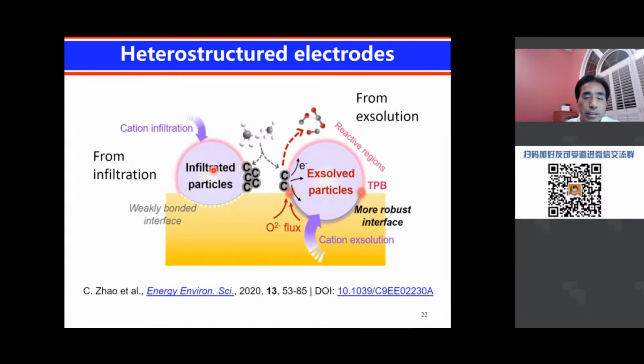Yeah? So here, just to schematically illustrate, you can introduce a catalyst by infiltration, and that will interact with the parent oxide and then create heterojunctions. Or by changing the process and condition, you can have exsolution or precipitation of cations from the parent phase and create nanoparticles on the surface. Either way, this will create the so-called heterostructure or heterostructured electrode. It is the junctures between two different materials where often you can have a uniquely designed catalytic property for the chemical and energy transformation process.